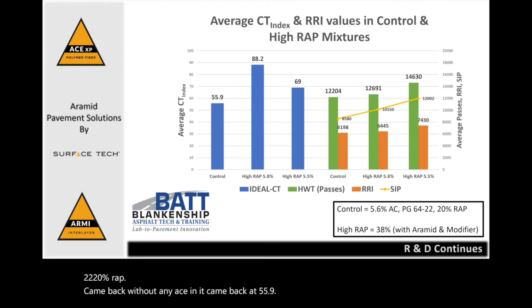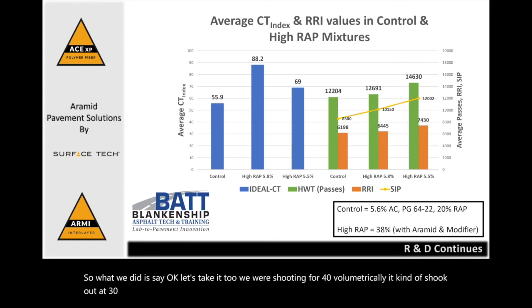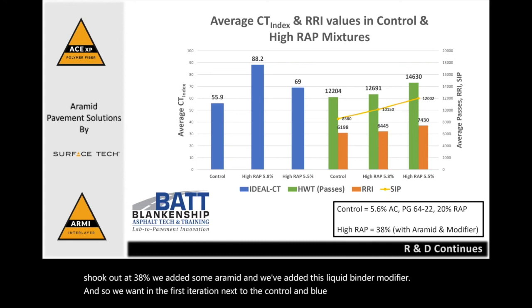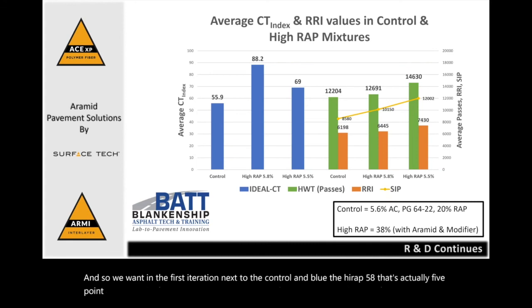So what we did is say, okay, let's take it to, we were shooting for 40 volumetrically, it kind of shook out at 38%. We added some aramid, and we've added this liquid binder modifier. And so we went in the first iteration next to the control in blue, the high RAP 5.8%, that's actually 5.8% of liquid AC. So we bumped it 0.2 in liquid AC, added the aramid, and added the modifier. And you can see, holy cow, we really provided quite an improvement in cracking.